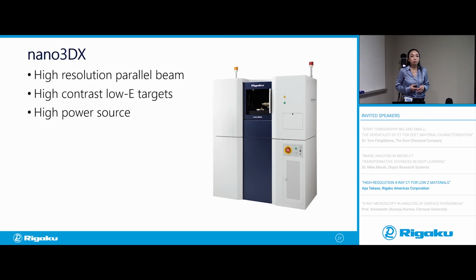And I think the average X-ray sources people use for cone beam geometry are probably about 5 to 100 watts. That's the general range. So you can see 1200 is really high for X-ray CT imaging. And again, high resolution imaging takes a long time in general. You can speed it up by using a high power X-ray source, and also by using faster detectors like a CMOS detector. So you can use that on the Nano 3DX as well.